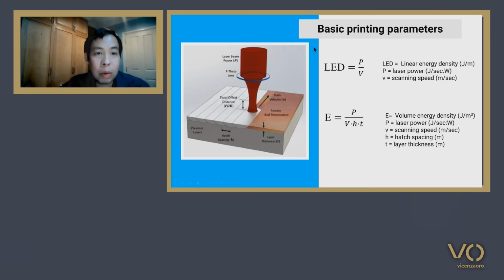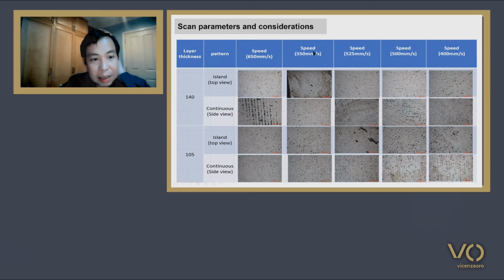So we do a lot of experiments like this. The layer thickness themselves, the patterns, these show only two patterns here. I will cover the scan strategies later, but we have the island and continuous scan at different speeds. You would see that there are different degrees of porosities here, and we are trying to accomplish at this point a fully dense sample.